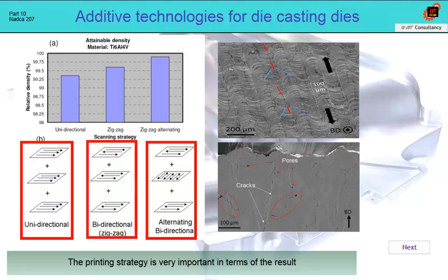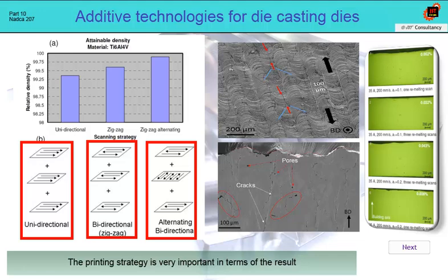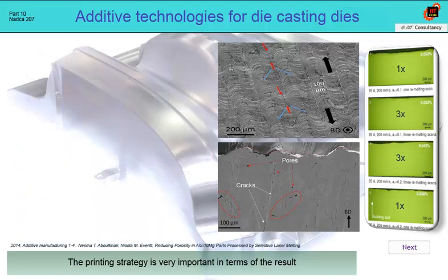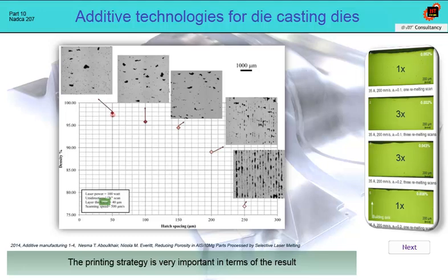Part of the printing strategy is the multiplicity of remelting, where one spot of the surface can melt once, twice, or even 3 times. This will, of course, be reflected in the porosity of the material and the number of defects after printing. As part of the printing strategy, the target density requirement is also set. As can be seen from the figure, with a layer thickness of 40 micrometers, a beam speed of 500 millimeters per second, and a laser power of 100 watts, a density of 98% can be achieved if the distance between individual traces is up to 50 micrometers. If we increase this distance to, for example, 200 micrometers in order to save time, then the achieved density of the material will be only 89%.